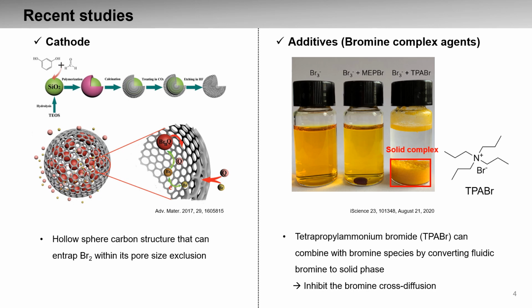Also, there has been a lot of research conducted on electrolyte additives, which are bromine complexing agents. In this paper, tetrapropyl ammonium bromide was used as an additive to the electrolyte. It can combine with bromine species by converting fluidic bromine to a solid phase, as shown in the figure. And this solid complex can interact in the electrode. It means that the TPABr can inhibit the bromine cross diffusion, and it leads to high reversibility.